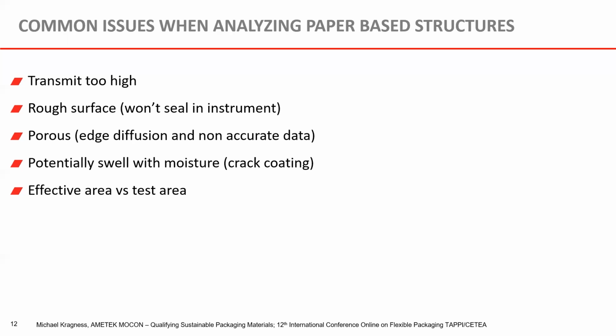In the presence of high humidity, you get the potential for the substrate to swell, because paper likes to swell in the presence of moisture. This could compromise your coating or crack your coating. Another method that you may use to test a paper-based material is that you may mask it. And what that will do, as I'll show you here shortly, is that you can have a scenario where the effective area of your sample contributing to your transmission rate is not the same as your defined area.